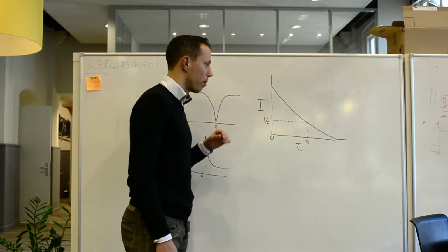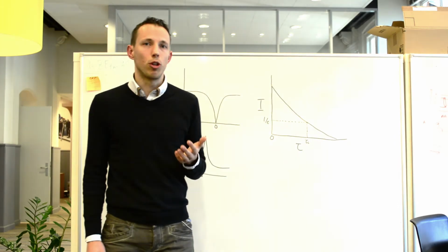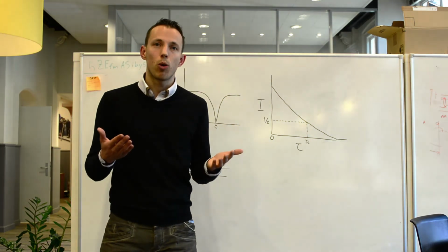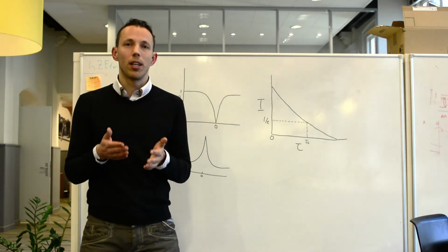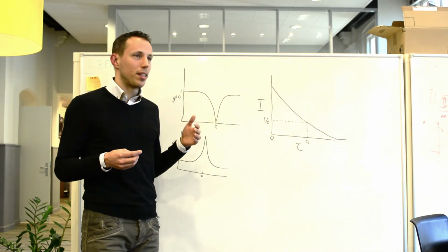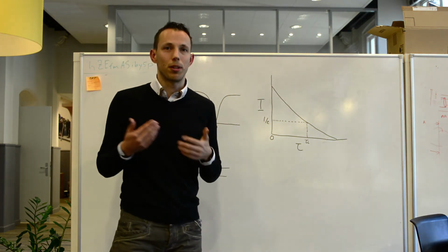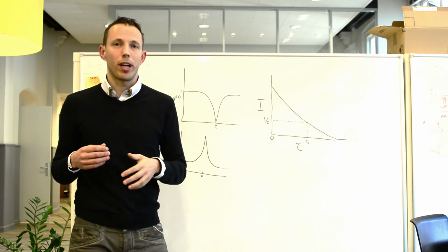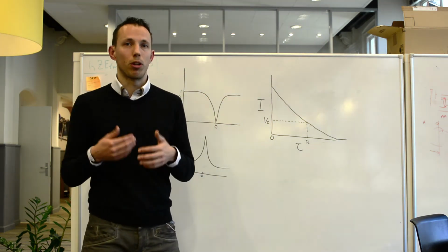Also, and this is maybe a more fundamental link, but the lifetime is also very much linked to the optical environment and to the local density of optical states. And that's a key quantity in optics that defines how strongly light interacts with matter and vice versa. And the lifetime can nicely gauge that, and so this is a very powerful method to dive into those types of effects and, for example, see how material behaves in the vicinity of a cavity or an antenna.